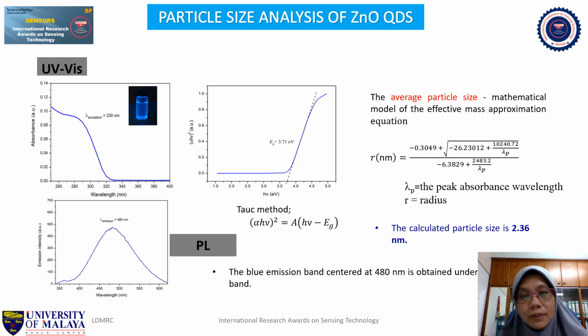We have used several methods to confirm the particle size of the zinc oxide quantum dots. The first method is known as the mathematical model of effective mass approximation. This is the equation that determines the radius of the quantum dot. In this equation, we need to know the absorption peak of the quantum dot, so we have to use UV-Vis spectroscopy to obtain the absorption spectrum. From there, we can determine the peak of the absorption, which is around 280. Then by using this equation here, we can determine the radius and hence the diameter of the quantum dots. By using that analysis, the particle size is 2.36 nanometer.